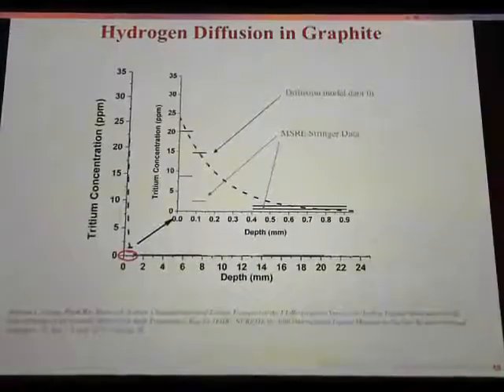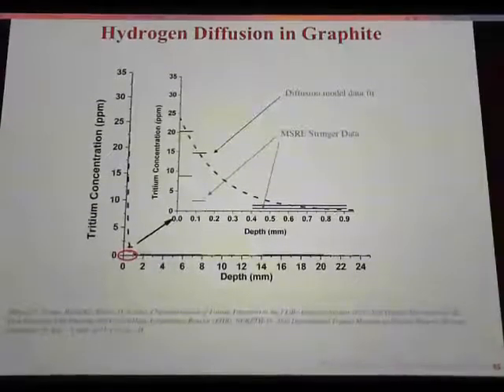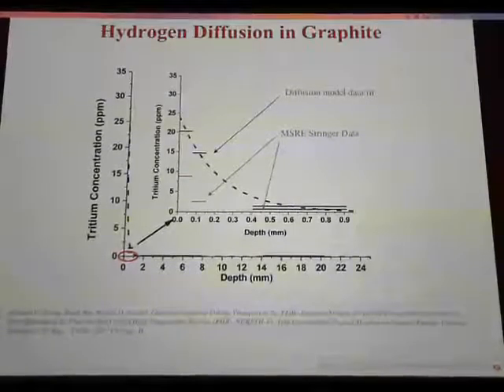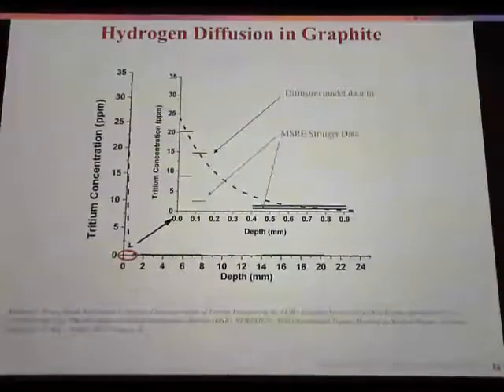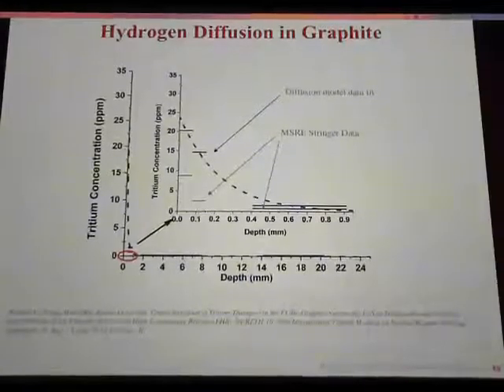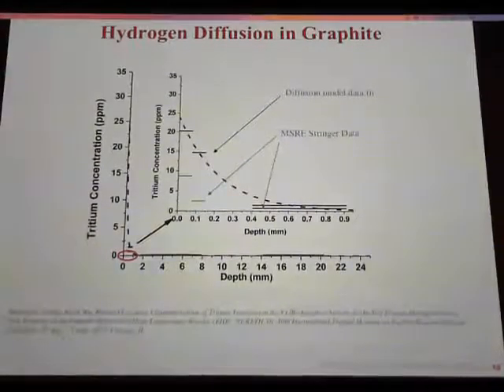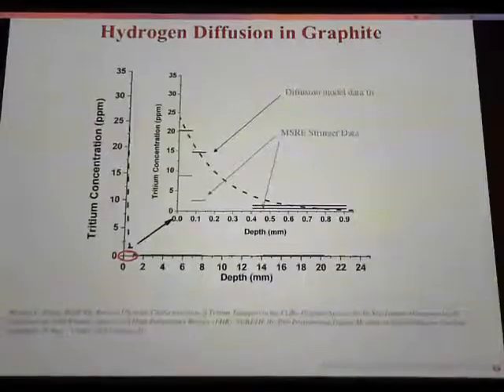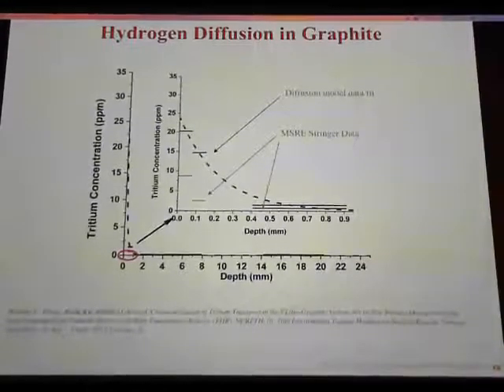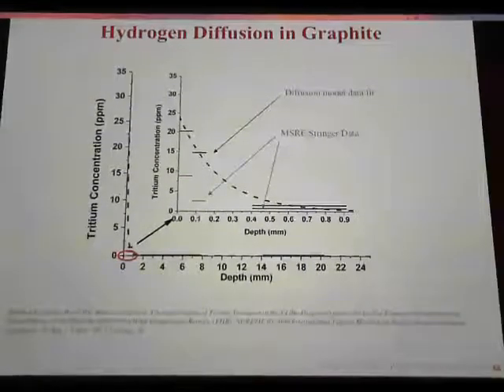So the first thing we did is there was one data set from the molten salt reactor experiment where they took a graphite stringer, a long graphite column that had been immersed in the salt for 1.5 years during reactor operation, and it had taken up tritium, and they took slices of it and quantified the tritium profile with that. And so we wanted to know if we could match their data with a diffusion model based on diffusion parameters for hydrogen in nuclear grade graphite.